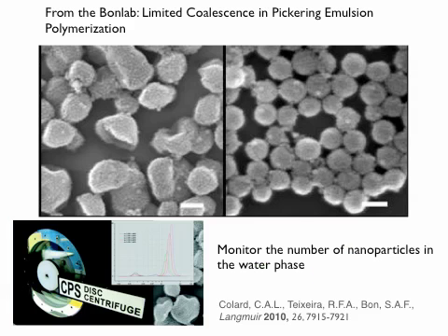So here you see a nice little application of this. We studied Pickering emulsion polymerization, so we wanted particles stabilized by small nanoparticles of silica. In that recipe, it was very, very important that we knew how many small particles were present. Because obviously, latex particles are growing, and because they grow, the interfacial area increases. If you want to have stability there, you want to decorate the full surface area with particles.